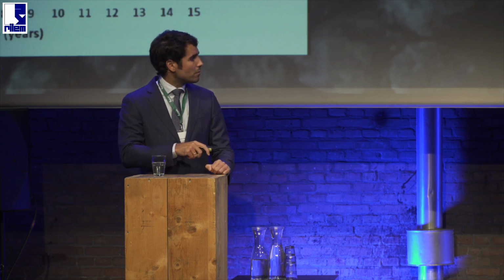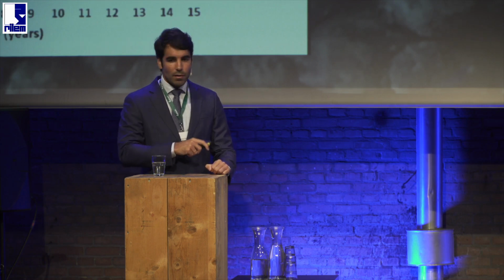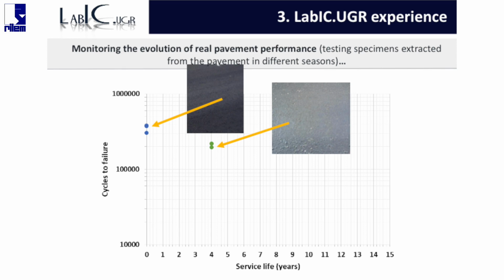Setting that in a graph of service life in years and pavement performance measured through the cycles to failure of the cores, we can determine the evolution of the mechanical performance of that real road in order to determine when is the optimal period to act.